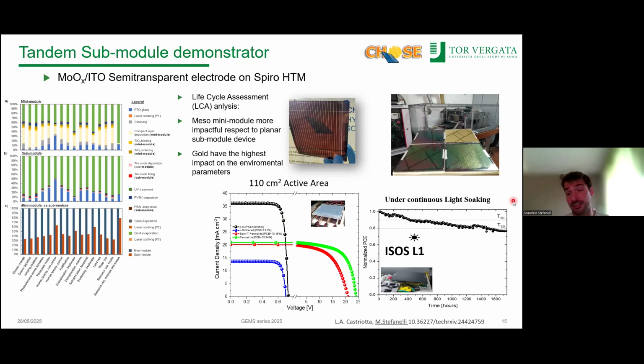The important thing is the stability that we got on this semi-transparent module, because the T80, in this case for the whole stack made in ambient air with 30% relative humidity, was reached after 1,200 hours. That is quite good.